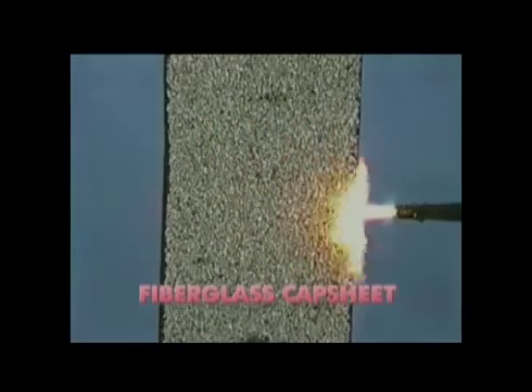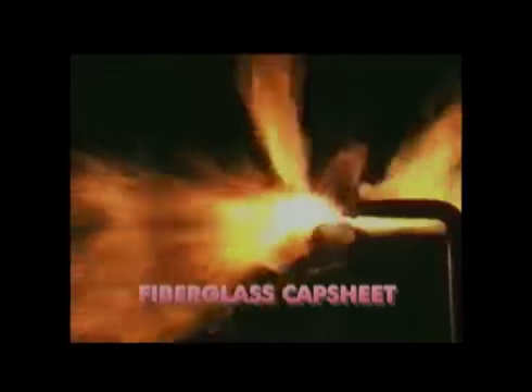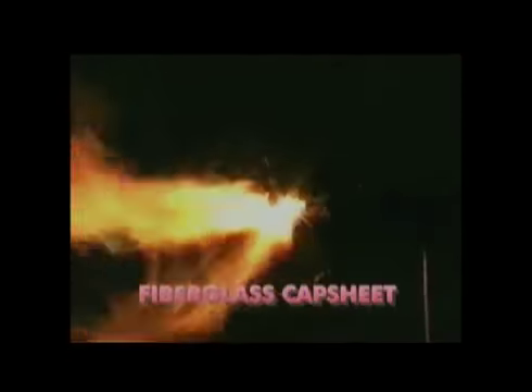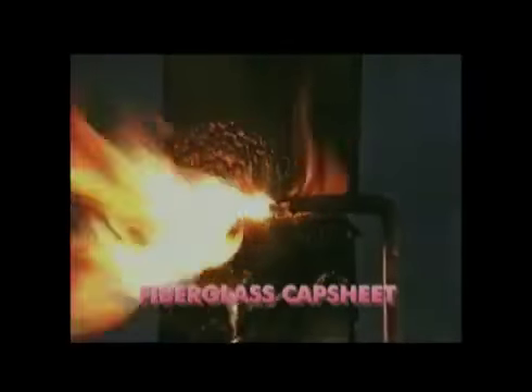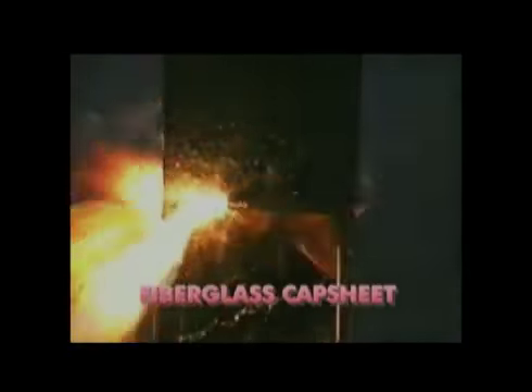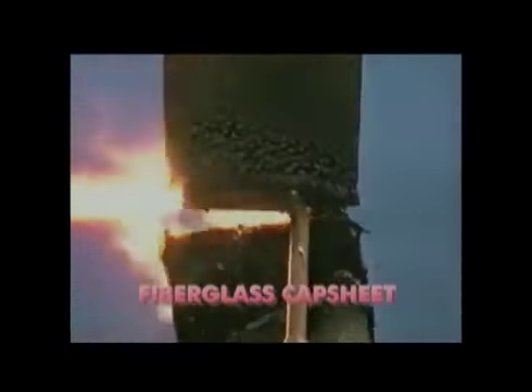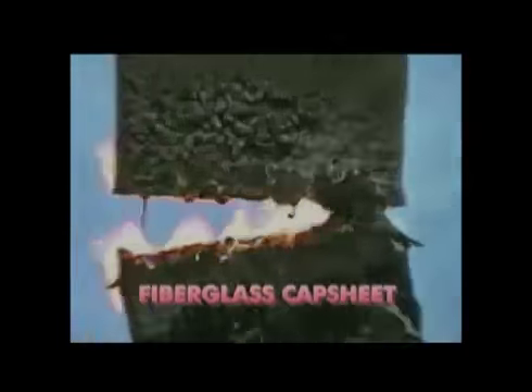If you could concentrate the heat and UV of years of sun exposure, this is what it might look like. The oils in the asphalt burn away, exposing the reinforcement to damage. Even though this built-up fiberglass roll system has the highest fire rating, UL Class A, it cannot stand up to this extreme test. But neither can 1/8-inch solid steel. But against WeatherWeld, the torch is stopped cold.